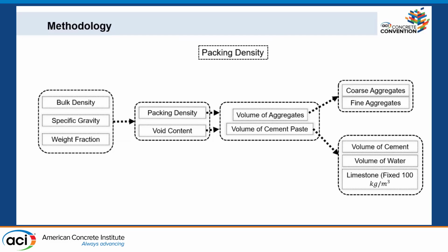For the packing density, it was also taken as a method, and we have got the bulk density, as I mentioned before, from which we can get the void content found in the packing. When we multiply with the specific gravity and the weight fraction, we get the packing density. From the packing density, we can also get the void content, which can be calculated as the cement paste. From that cement paste, we have found the amount of cement and water, and the amount of limestone, we have already fixed for our cement paste. In the volume of aggregates, we have found the coarse aggregate and the fine aggregate percentages, comparing it with the optimization curves.